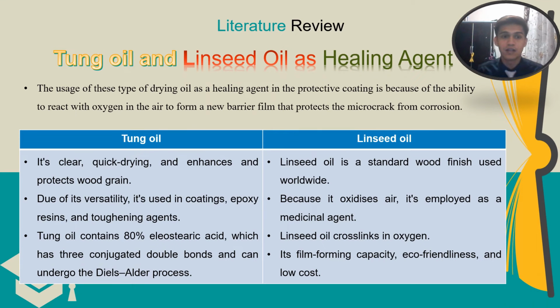The literature review for tung oil and linseed oil as a healing agent. The usage of this type of drying oil is because of the ability to react with oxygen in the air to form a new barrier film that protects the microcrack from corrosion. Different properties of tung oil and linseed oil: tung oil contains 80% of eleostearic acid, which has 3 conjugated double bonds, and the linseed oil has a cross link in the oxygen, which has not more than 2 double bonds.